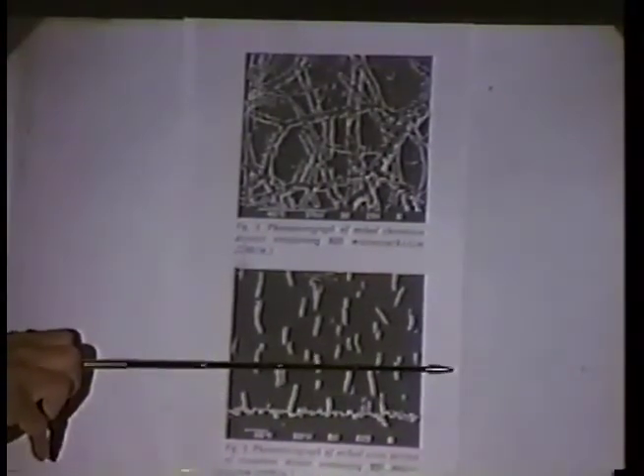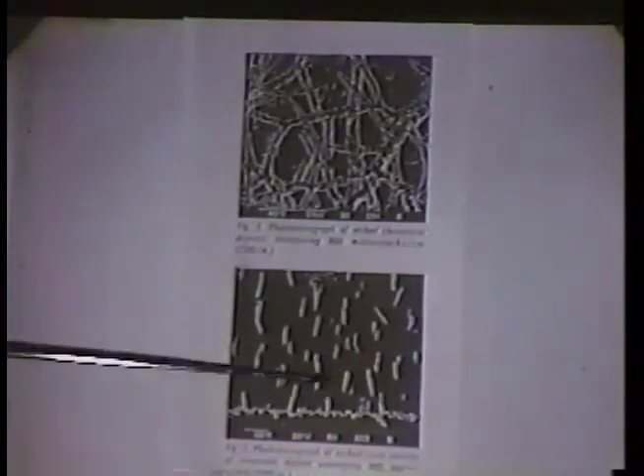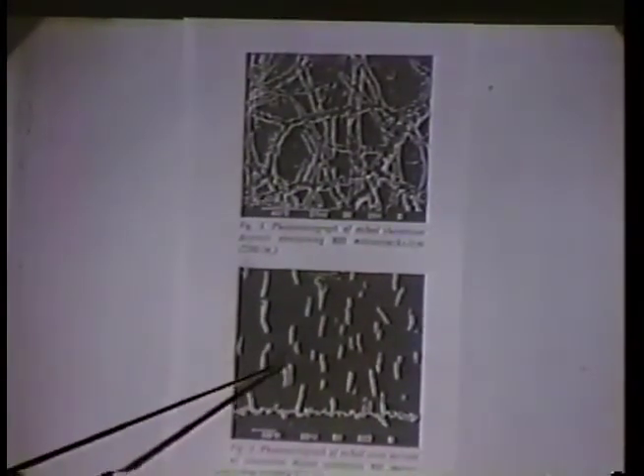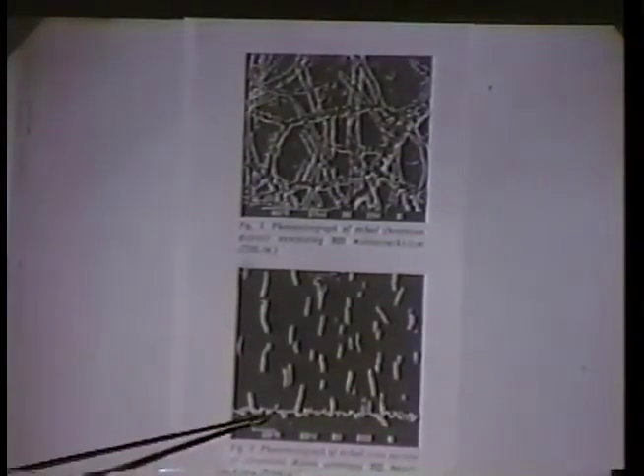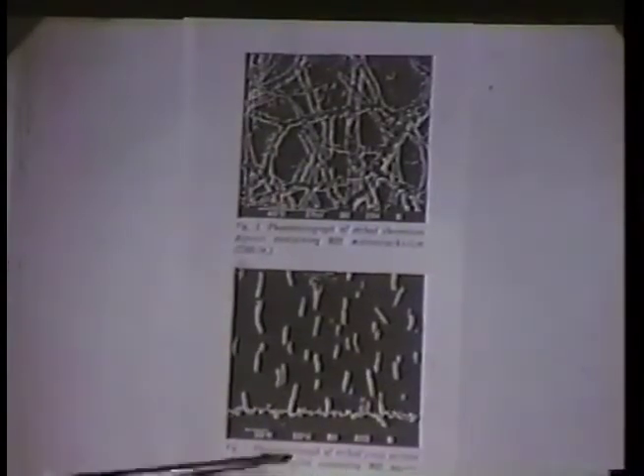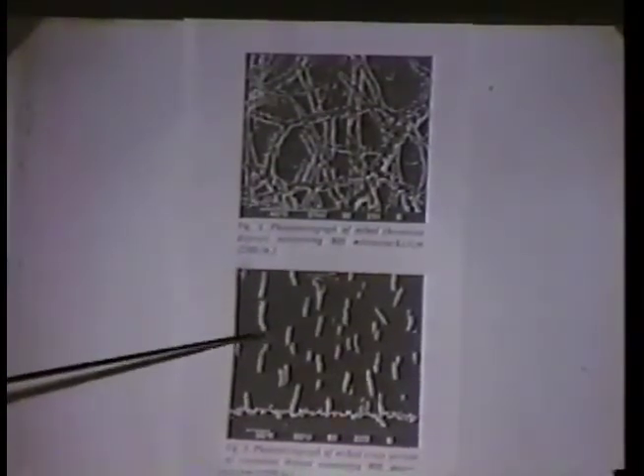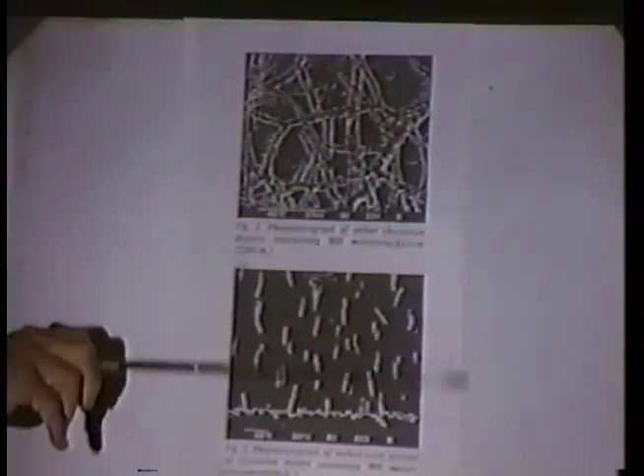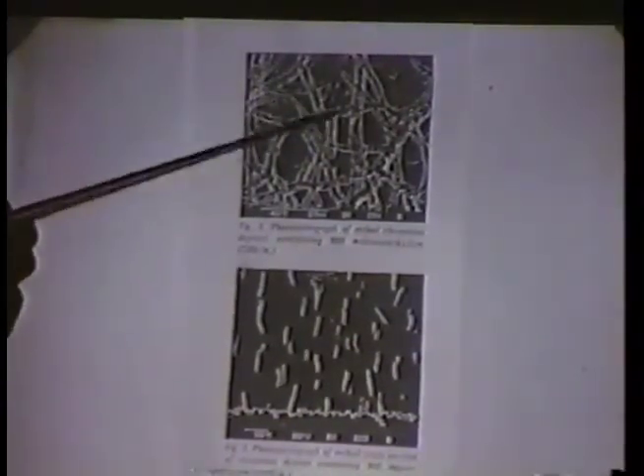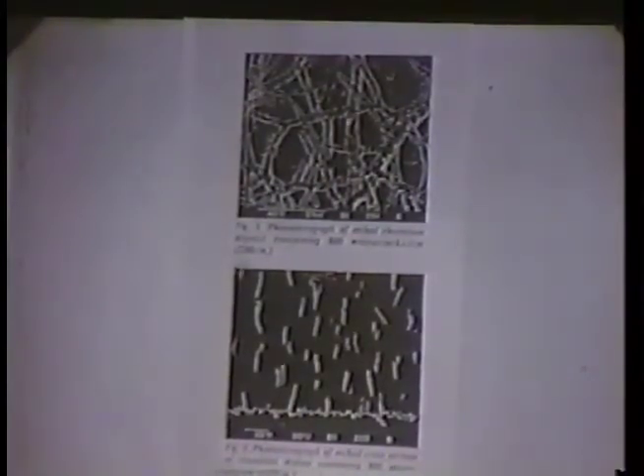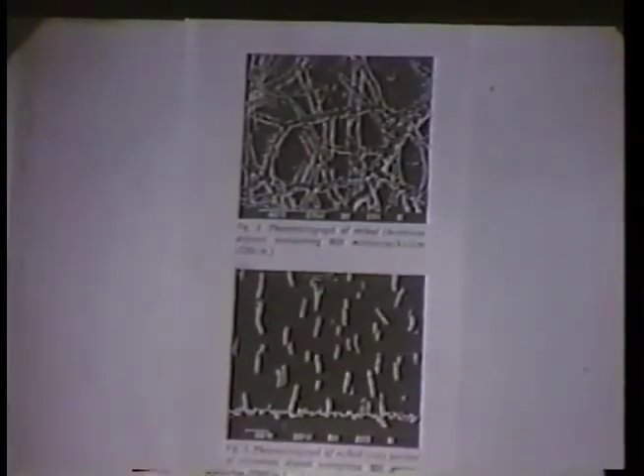And you can see rather distinctly that there is some layering that takes place as those cracks form, but you don't see any of these up in the thickness radiating down into the base metal. You only see that in the first tenths of a thousandth of chrome. From the side view, you see this kind of stress relieving as that chrome builds up. From the top, it looks like this through a microscope, looking down on it. That's totally natural and present in every kind of chrome, including decorative chrome. That's why, on the old bumpers, some of you guys remember chrome bumpers, in time you'll see that pattern develop as the water gets behind it.